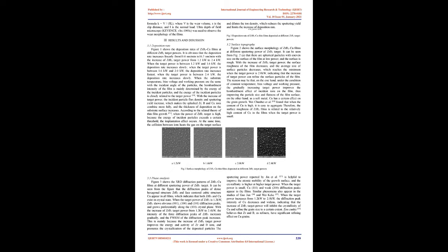Keep the bias voltage of 800 V, change the pressure to 0.6 Pa, and turn on the pulsed DC Cu target for 8 minutes. In order to avoid resputtering, the bias voltage was adjusted to 150 V, the pulsed DC ZrB2 target was turned on, and the ZrB2-Cu thin film was deposited. The rotating speed of the rotating frame was set to 40 rpm, and the deposition time was 240 minutes. ZrB2-Cu thin films with different relative copper contents were prepared by changing the sputtering power of the ZrB2 target. The deposition parameters of ZrB2-Cu thin films are shown in Table 1.